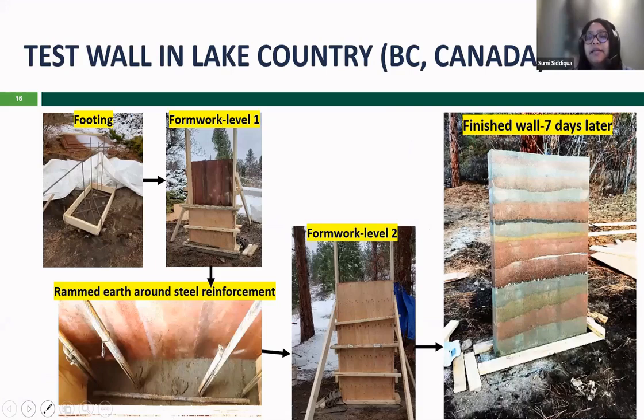Now we run the test sample in Lake Country, another city beside Kelowna, because the contractor who was building the rammed earth wall got a client in Lake Country, and they used our recipe and constructed the wall. So the only observation from this after a long period of time, because this was done in 2021: when we constructed that, it was fine, but over the period of time, because of having some bentonite in this material, it started to show some long-term environmental impact. Some small cracks started to develop after it faced several freeze-thaw cycles, natural freeze-thaw cycles from the weather point of view.